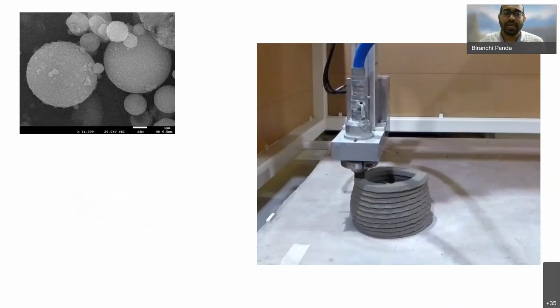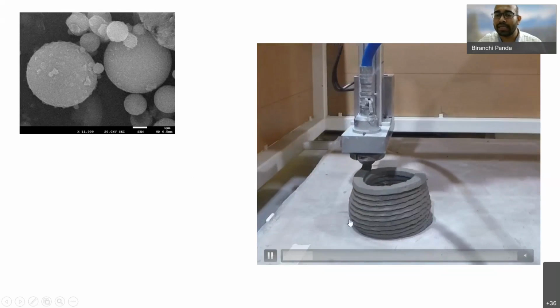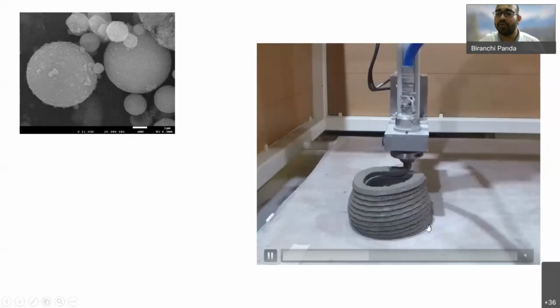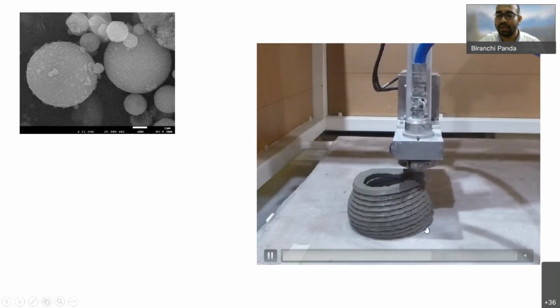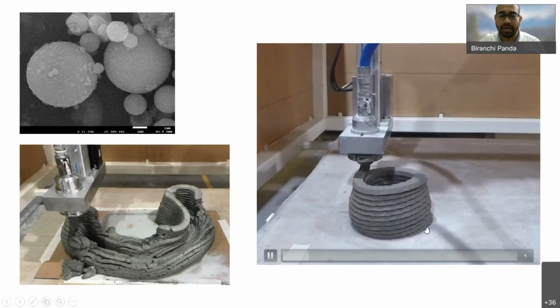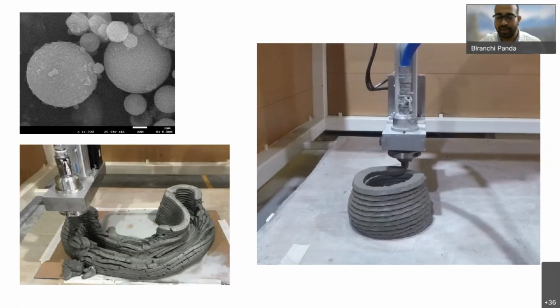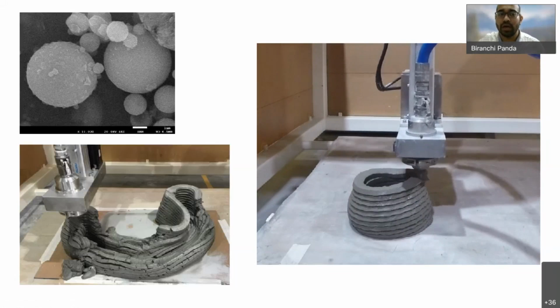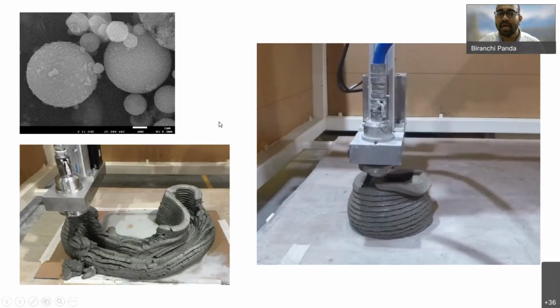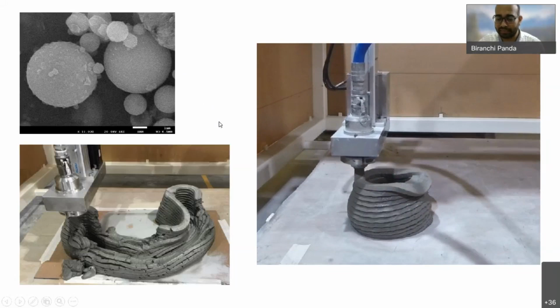So what happens when we replace the cement with such particles, which are spherical in nature? They can easily flow away, so ultimately the yield stress becomes very low. If I deposit more layers, it is going to collapse after printing a few layers. If you see the structure, it is completely collapsed after printing a few layers. We still wanted to use this industry waste in our mix design, because our goal was to create a sustainable mix. For that reason, we tried to investigate what else we can do to improve the buildability.